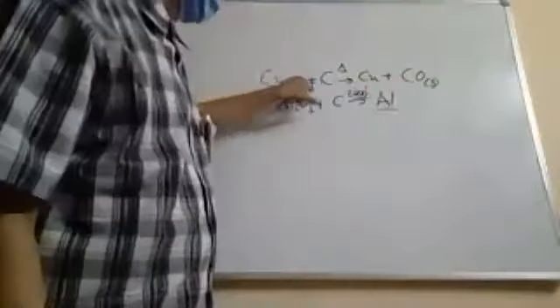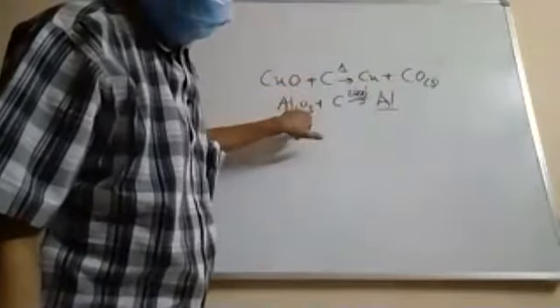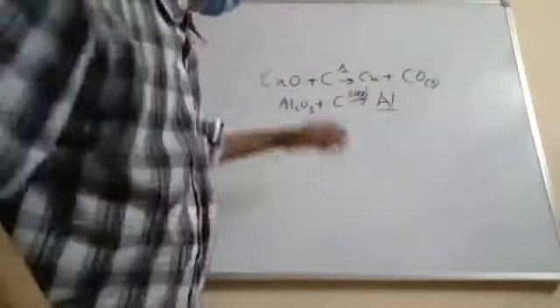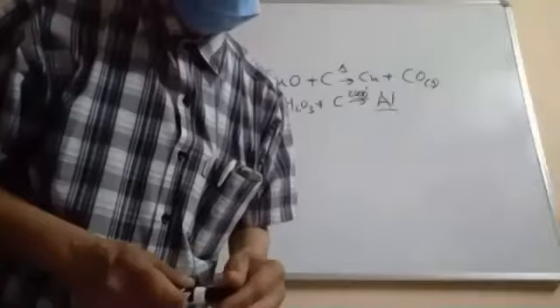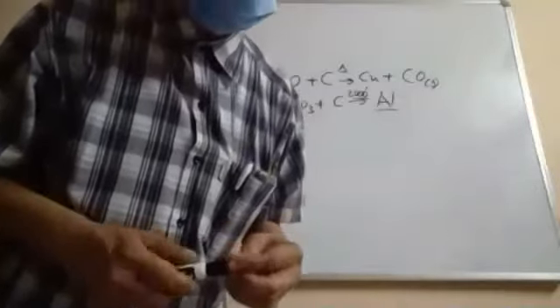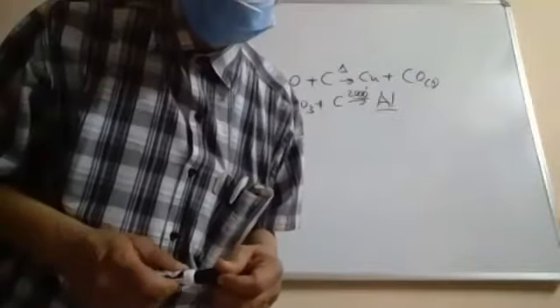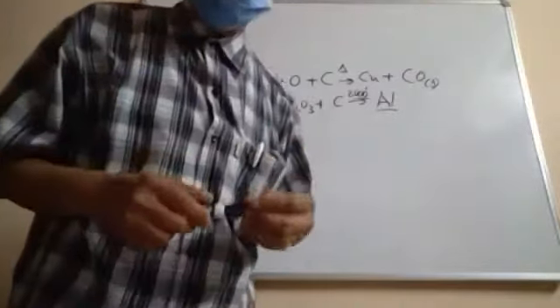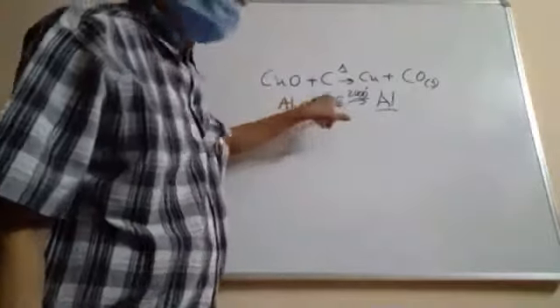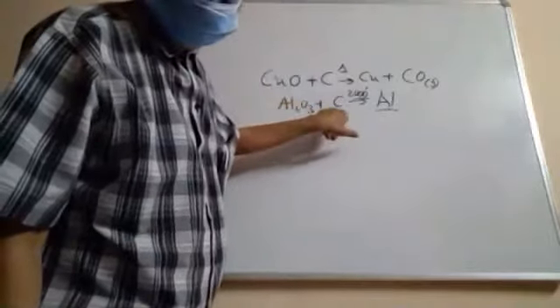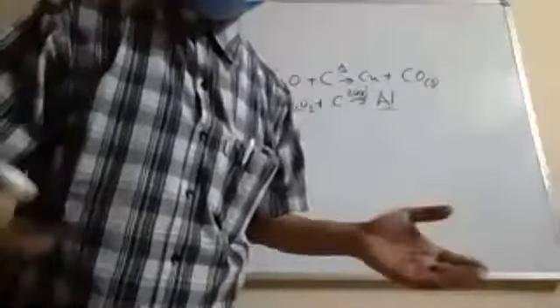That's extremely high temperature. So copper, on the other hand, requires low temperature, while aluminum oxide requires extremely high temperature. The big problem with such high temperatures is that most of the aluminum oxide sublimes. So the amount of aluminum metal you get is extremely small. In the past, aluminum used to be an expensive metal because it required extremely high temperatures, and the amount of aluminum oxide that survived such high temperatures was so small that the amount of aluminum we were getting by carbothermal reduction was very small.